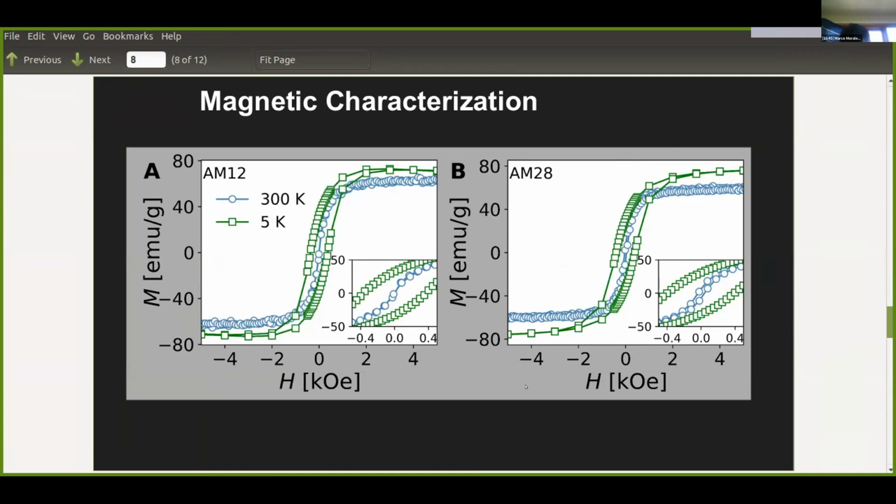Then we measure the magnetization curves as a function of the field at room temperature and 5 Kelvin. For this system, it is characteristic to observe a hysteresis loop in the blocked regime. From the measurement at room temperature, for example, we find, by zooming in on the larger particles, that a small part of the system is in the blocked regime.